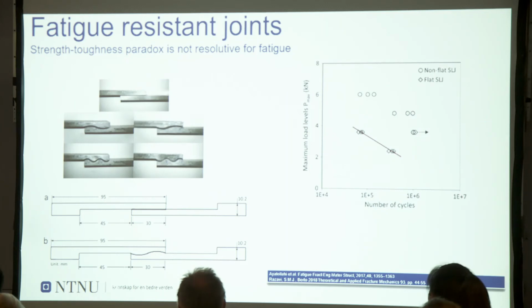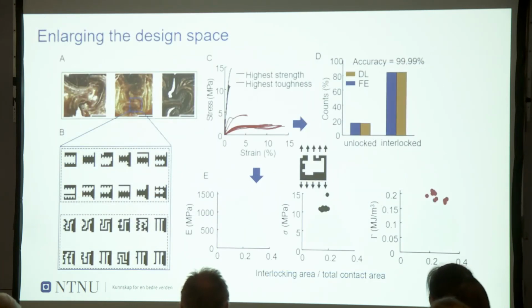Although the strength and toughness paradox is not resolved for fatigue design, of course, having a kind of interlock surface at the macro scale allows us to improve the fatigue life substantially. So, keeping this in mind, starting from this bio-inspired case, we have tried to apply machine learning techniques or data-driven methods to enlarge the design space and obtain a set of new design structures that were able to improve the strength and the toughness in parallel.